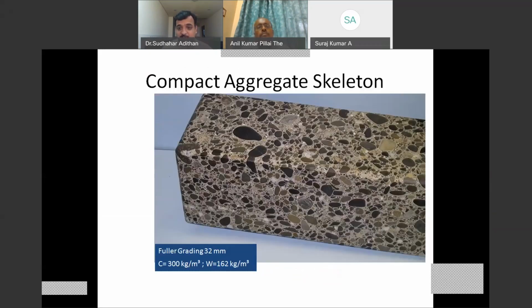We were just talking about grading. This is a nice and recommended grading system where you can see this is actually a cut section which is polished. It is not a mosaic or anything. It's a regular concrete element which has been cut and polished. You can see the presence of particles of all sizes, especially the coarse aggregate. This means it's a more practical grading. This will give you a very dense concrete microstructure.